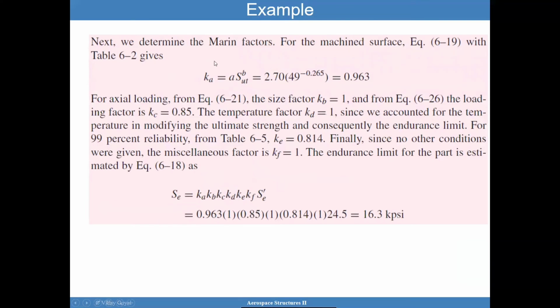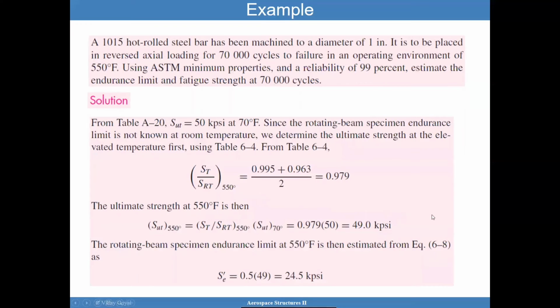So then we have to use the Marin factors for machined surface, and then we get a value of 49 to these values here. 0.963 is Ka. Since it is an axial loading condition, the size factor is 1, and the load factor becomes 0.85, as we had discussed before. The temperature factor kd is already accounted for, so you can make it 1, so no issue there. For 99% reliability, use a ke of 0.814, and we have nothing else to consider, so then see how quickly this 49 drops.